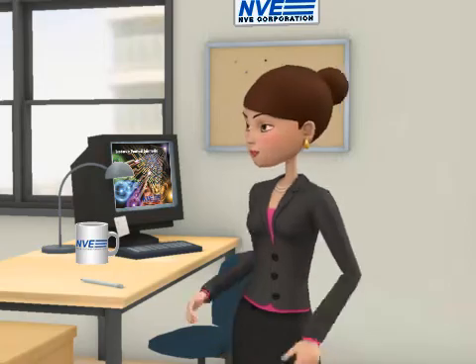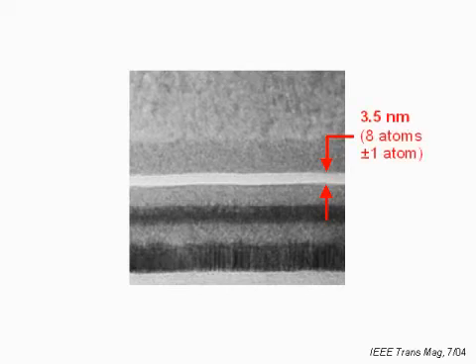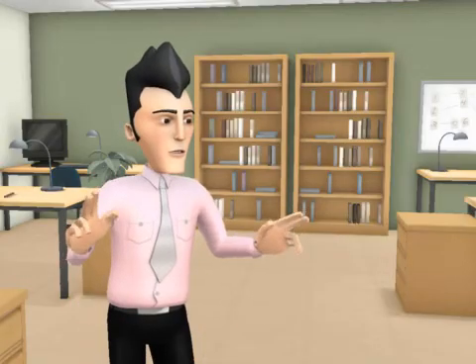Here's an SEM of an actual MRAM tunnel junction made here at NVE. This white stripe is an aluminum oxide tunnel barrier, eight atoms thick. This is probably magnified nearly a million times on your screen, so an eight-inch wafer would appear a hundred miles in diameter. We have a separate video explaining tunnel junctions.